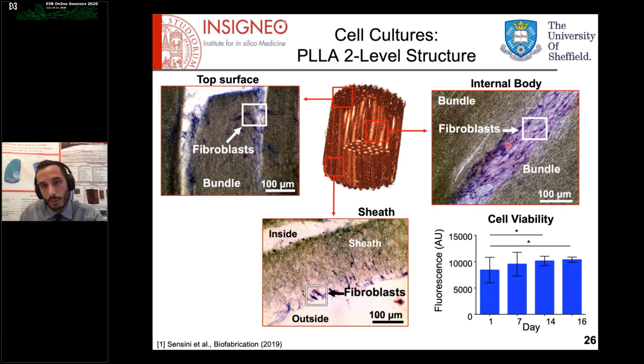You can see that fibroblasts are able to infiltrate inside the structure from the top and start to grow on the nanofibers, elongating their bodies and nuclei in the direction of the nanofibers, similarly to what happens in physiological tissues. Moreover, the fibroblasts were also able to grow on the electrospun membrane and slowly infiltrate inside it through the porosities, arriving inside the scaffold.